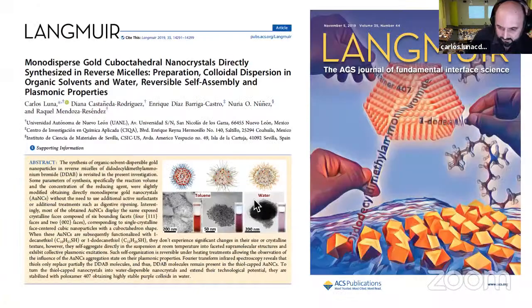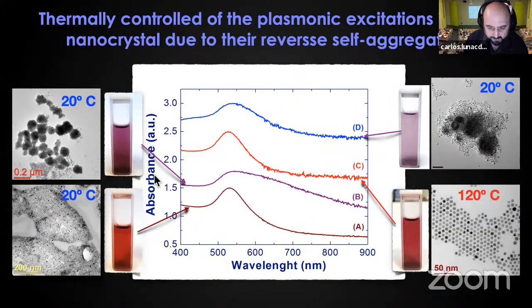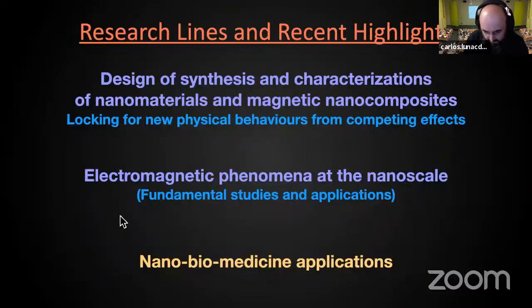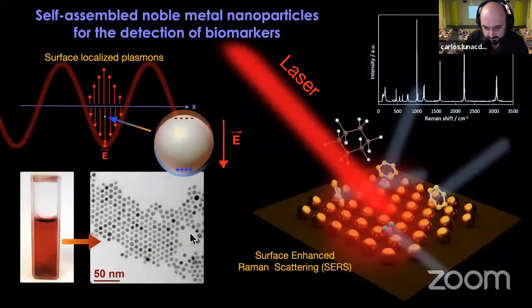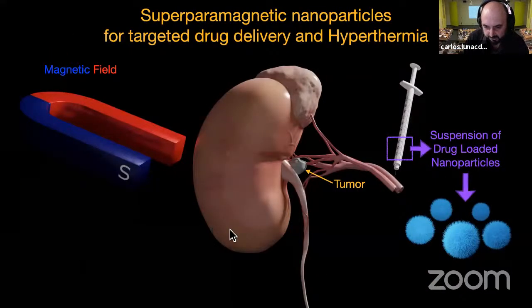We prepare colloidal gold nanocrystals. We control aggregation states by temperature, so we can modify the plasmonic excitations via changing the temperature or with chemical agents. Other research lines are the use of self-assembled noble metal nanoparticles as platforms of surface-enhanced Raman scattering for the detection of biomarkers, superparamagnetic nanoparticles for targeted drug delivery and magnetic hyperthermia.